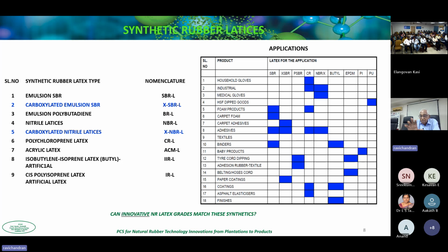I'm not covering synthetic rubber latexes now, but here you've got 9 of the major synthetic rubber latexes. The 2 in blue, carboxylated emulsion SBR and nitrile latexes, are the most popular. Carboxylated nitrile latexes are now used very much in gloves. It's a big use in gloves, and it has displaced natural rubber gloves from 100% down to about 50%. So now nitrile and natural rubber latex are almost equal in the glove sector, but the glove sector itself has grown so much that there's been no drop in consumption of natural rubber. In fact, more natural rubber is used in gloves today than was used 10, 15 years ago.